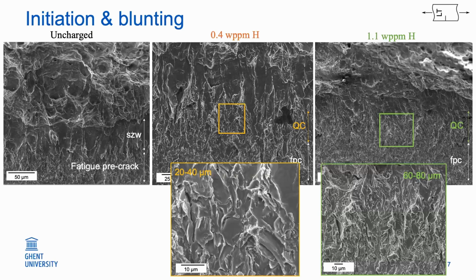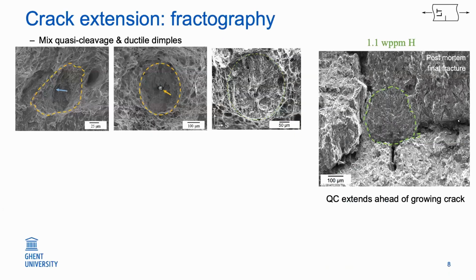Very small regions just past the fatigue crack of quasi-cleavage. And this region becomes bigger the higher the hydrogen concentration becomes. But then we do transition back to a ductile mode of crack extension. For the crack extension then, on the fractography, we can find a lot of quasi-cleavage regions.